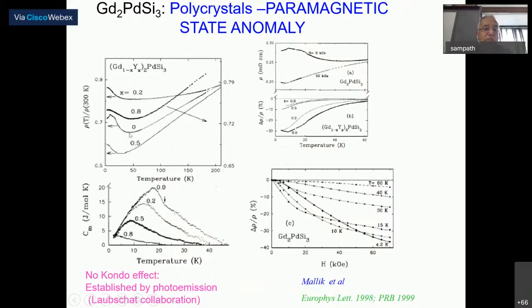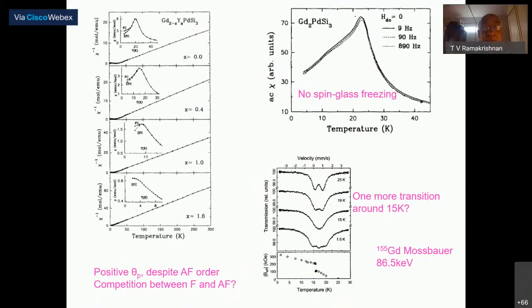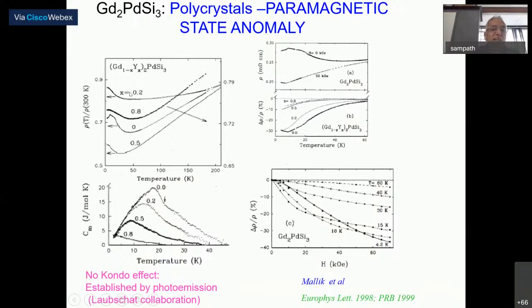Below something like 40, 45 Kelvin, however, there's an upturn here. There's a magnetic ordering at this temperature, 21 Kelvin. This is very, very surprising. And then when you dilute by yttrium, even then the minimum is still there. And you could see here, sorry, my cursor is okay. So the minimum still persists even when you have only 20% of gadolinium here.